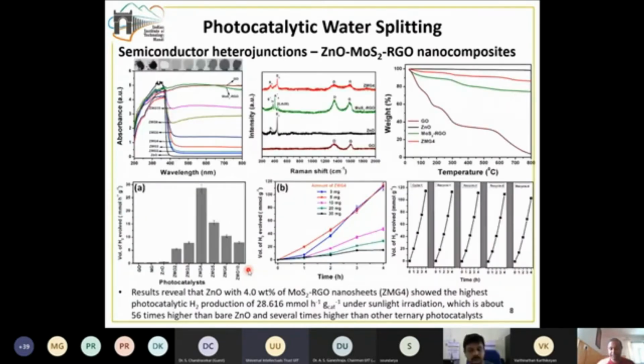Then we did this Raman spectroscopic analysis, wherein we could clearly see the D and the G bands of the reduced graphene oxide. When the graphene oxide gets reduced, the ratio between the D and the G bands changes. That is a proof here. And we could also see certain bands corresponding to the MoS2, which indicates that all three components are present in our material. So this is also a proof for the successful synthesis of the nanocomposite.